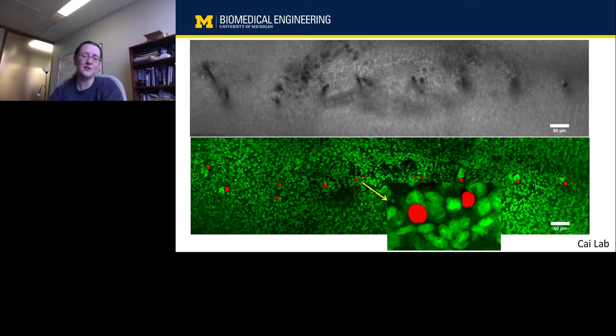So you can see here's two electrodes. They moved a little bit in implantation, and they ended up about 30 microns apart. And there's two neurons settled in between them at 11 weeks after implant. Again, I mentioned we can circle these holes all the way down, and we believe we can identify the tips of the electrodes because these holes disappear pretty quickly. And we've used that to start doing 3D reconstructions of the neurons surrounding the electrode tips. So let me go ahead and play a movie of what that looks like.